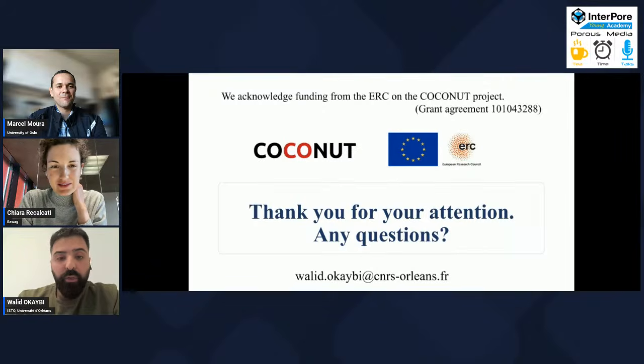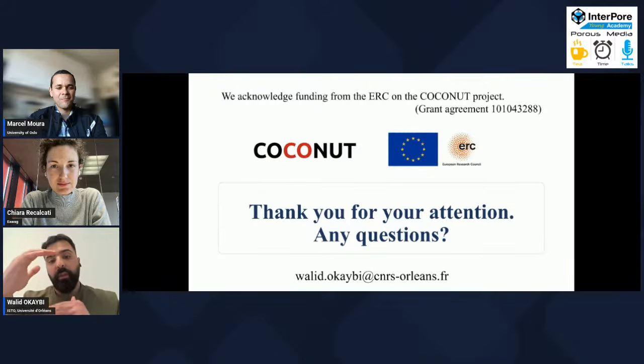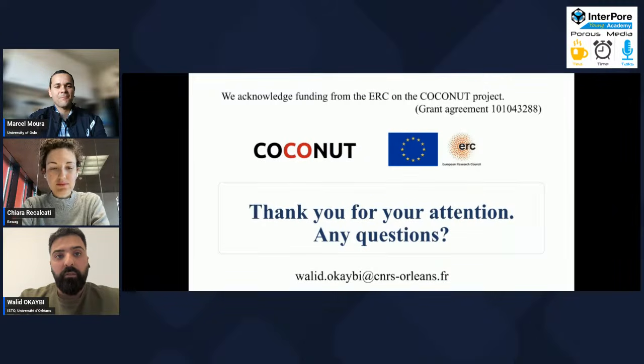So for sure, the geometry will affect the formation of these dendritic structures. Especially because in our study, the mean pore diameter was around 100 micrometers. So for example, if we have smaller pore diameters, it means at a specific flow rate, if we use this specific flow rate in another heterogeneous porous domain, which is more confined or has a higher constriction ratio, I think that will increase the velocity, and by increasing the velocity, it will affect the growth of the dendrite formation. But we didn't do experiments on different types of geometries. We just stick to simple geometries in order to isolate conditions, which is the single grain collector, and one heterogeneous porous domain with a specific pore diameter.